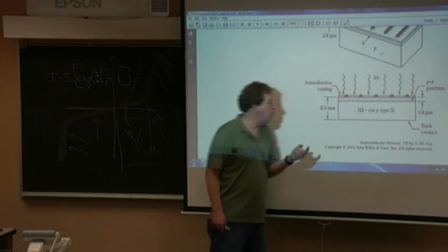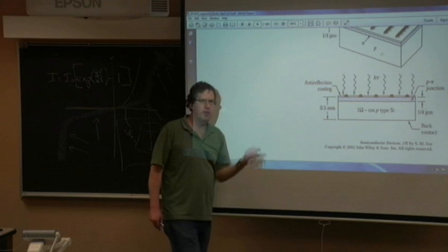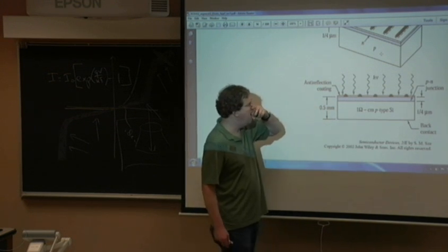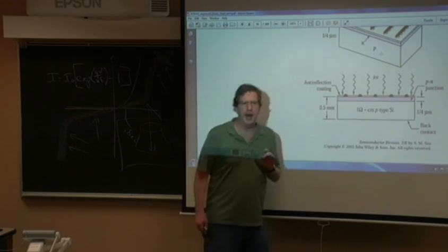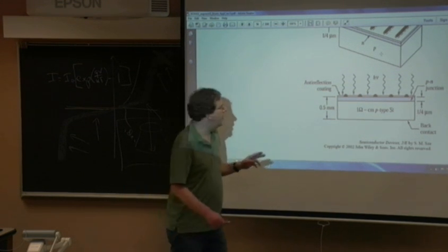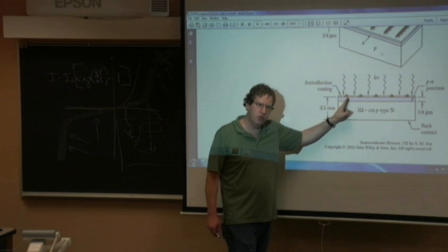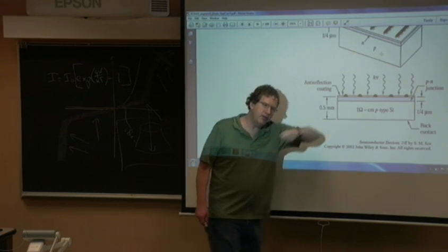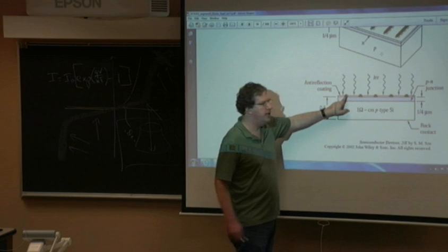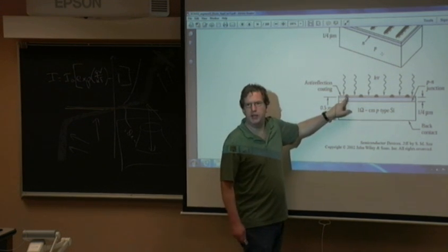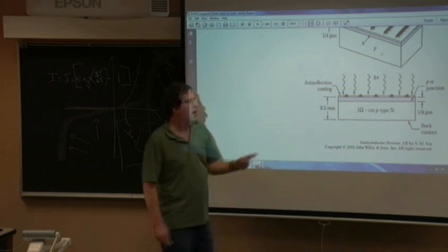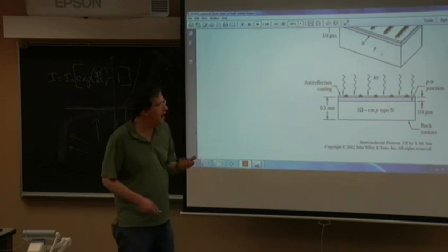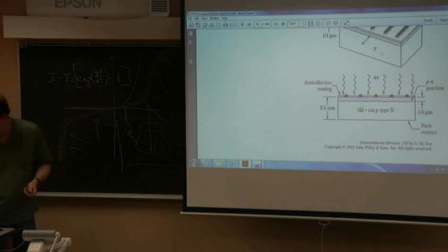printed. And the beauty of this, one of the things that started to bring the cost down in silicon solar cells, is this silver paste. This metal paste also acts as an acid etchant, and it will actually etch through that SiO2 glassy layer at the surface. So you just screen print it on, it etches through the glass, and then eventually it gets neutralized. And when it cures, you're left with the metal lines you want, grid lines. So all in one step, I have etched through the SiO2 and formed my grid lines. And it's innovations like that that are helping propel the silicon solar cell industry.